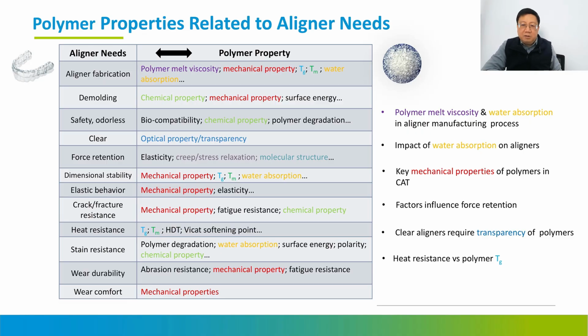So when the practitioners want to show us how to move the teeth, the best way is to use very moderate forces. For example, I give some references. If you look at the mechanical properties of single layers, the stretch modulus of TPU is something like 45 megapascals, and polyester is about 41 megapascals. But if you make a multi-layer, it would be something like 25. When you wear it, you can see the difference in comfort is quite big.